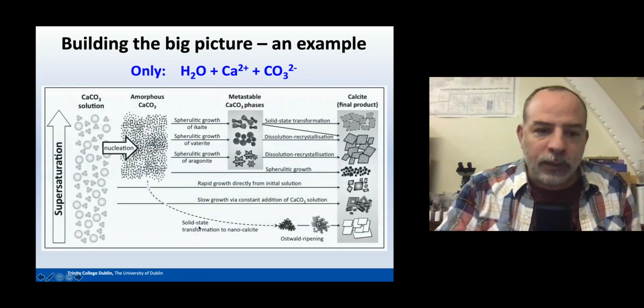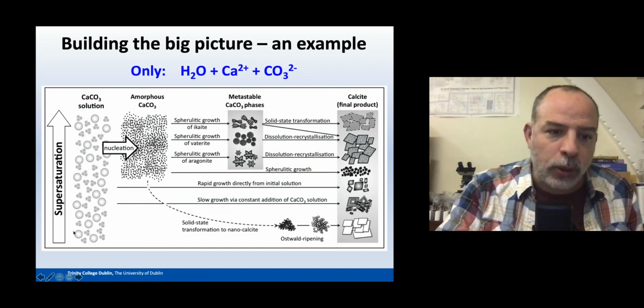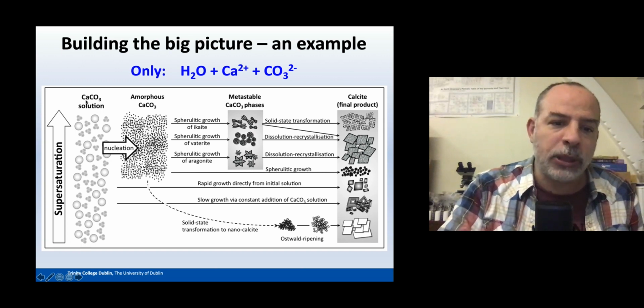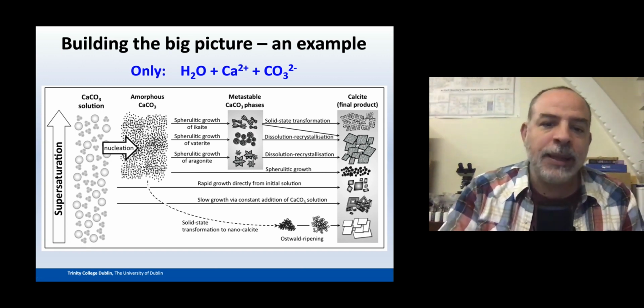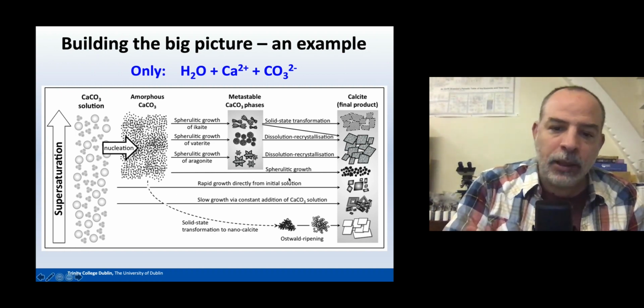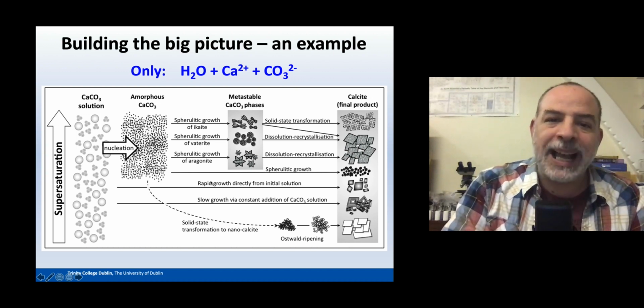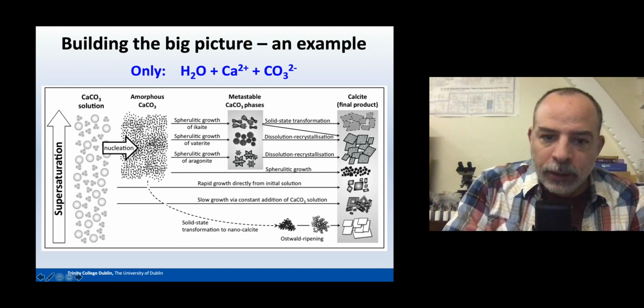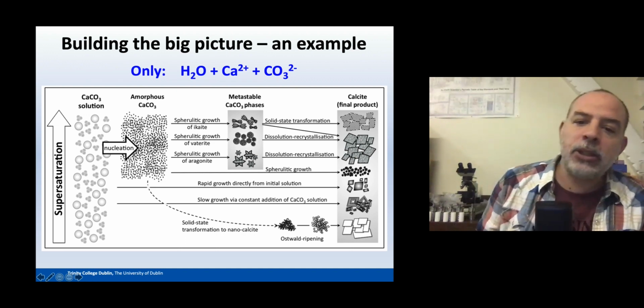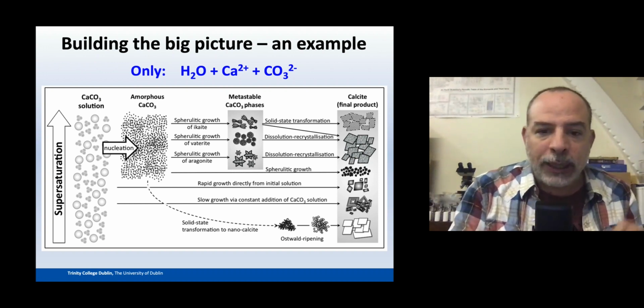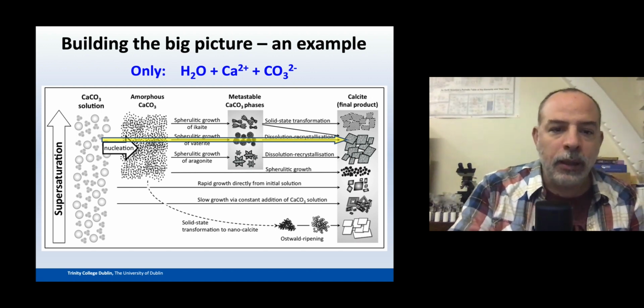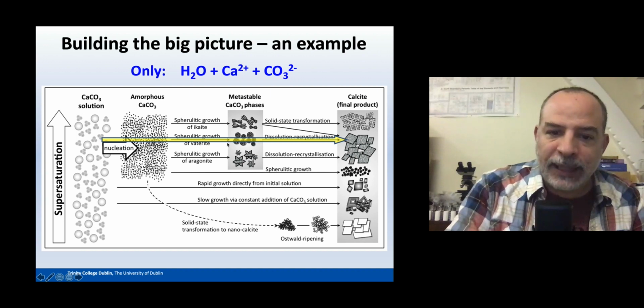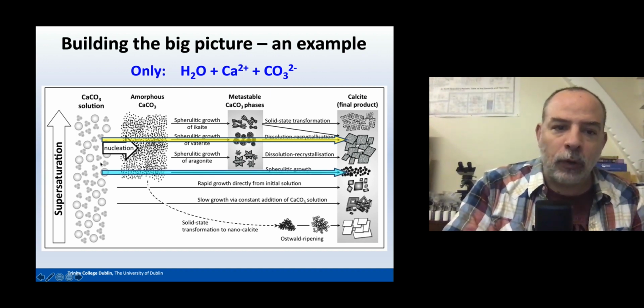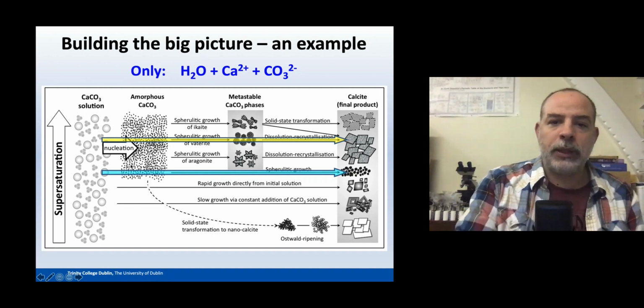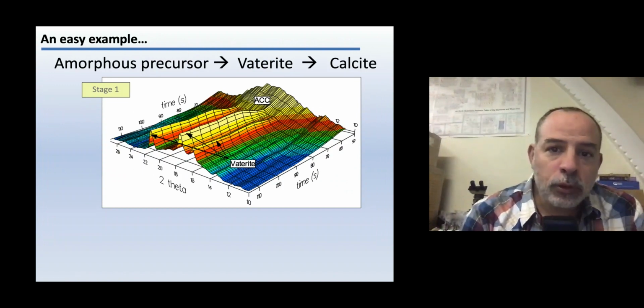Okay, so here you have a calcium carbonate solution, and this is showing you this solution as a function of supersaturation, low supersaturation, high supersaturation, and there are many different crystallization pathways taking place depending on supersaturation. Sometimes you can directly form calcite from solution, okay? Sometimes you form calcite via an amorphous phase, and sometimes you form calcite via an amorphous phase and some metastable intermediate phases that form quickly by spherulitic growth and transform into calcite via dissolution and recrystallization. Okay, this is a very well-known picture, and what I'm going to show you is what happens following this branch here. Okay, the crystallization from amorphous phase to calcite via vaterite, and also here the crystallization of calcite directly from an amorphous phase.